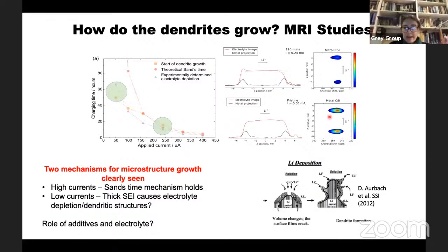And the reason for that is this wretched thing, the SEI, the passivating layer that I just keep going on about. When it grows, it's this inhomogeneous mess, and it results in inhomogeneous transport through it. And so you get hot spots in it. When a hot spot forms where maybe it's thinner, then the dendrite starts to grow. And so the challenge here is to really work on the nature of this SEI to stop dendrite formation